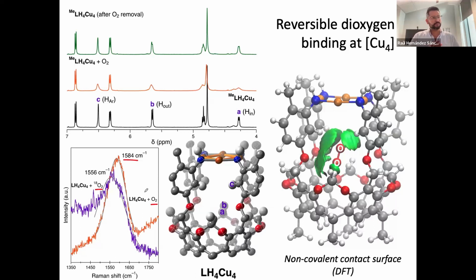So interestingly, we don't see electron transfer to dioxygen, right? Which is one of the first things that we were expecting, given that this is an all copper 1 species. So why is that happening? We don't know, but we may have a hint as to what is involved in that. Keep in mind that in all of these clusters that I just showed you, the metal plane is almost perfectly planar. The angles between nitrogen, copper and nitrogen are on the order of 177, 178.